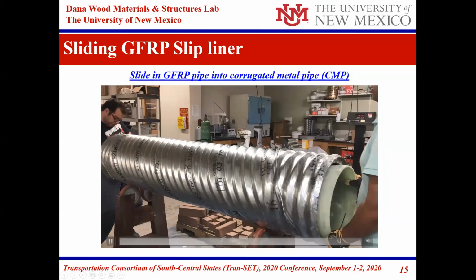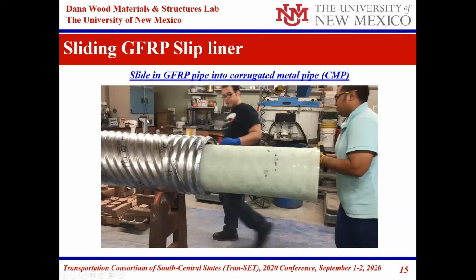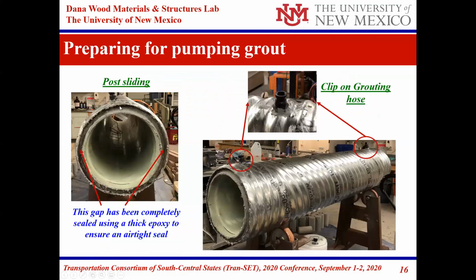You can see here the pipe after sliding, we basically close the ends. And that's going to be exactly the way it would be done on site. We close the end using a thick epoxy and wood. And there is now a gap between the GFRP pipe and the corrugated pipe here. Again, we've done testing for both, as you will see in the next slides, this being a corrugated metal pipe or a corroded corrugated pipe.